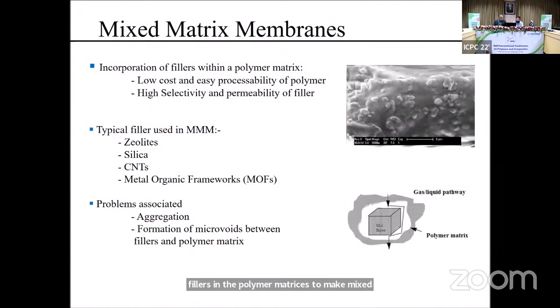At the Membrane System Research Group, we are focusing our effort on all these three different areas. We are working on tailored and functionalized polymers. We are working on ionic liquid-based membranes, and a lot of our effort is being dedicated to mixed matrix membranes, where we are using high-performance porous fillers in the polymer matrices to make mixed matrix membranes. As I mentioned previously, these membranes combine the low cost and easy processability of polymers with highly selective and permeable porous fillers. As a result, a composite is generated which comprises a polymer matrix in which we have a dispersion of inorganic fillers.